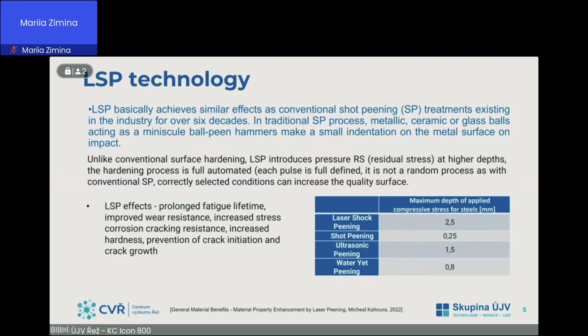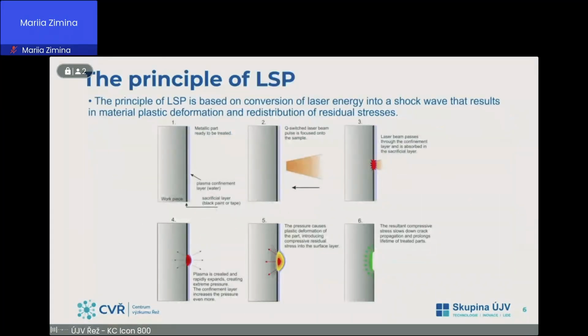On the right is the table with 4 peening methods: laser peening, shot peening, ultrasonic peening, and water jet peening. And on the right is the maximum depth of applied compressive stress for steels. You can see that laser shock peening has 10 times more depth compared with shot peening. And the maximum residual stress is higher than shot peening. And of course, the LSP effects prolong the fatigue lifetime. It's very similar with classical shot peening, as you know.